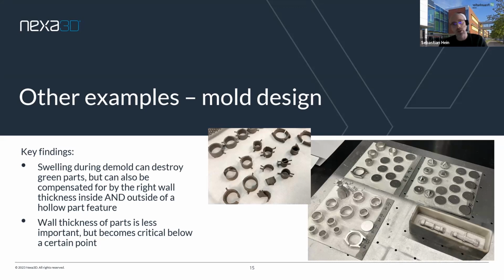So there is still a learning that we have to do, but as you can see more in the back, we could really make a lot of parts that were perfectly fine. And the interesting thing is that really all the features that you have inside your printed mold, they translate perfectly to the feedstock. And this is good to know and very important to know, because if you skip to the next slide.